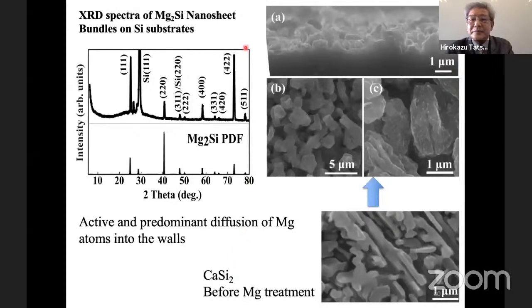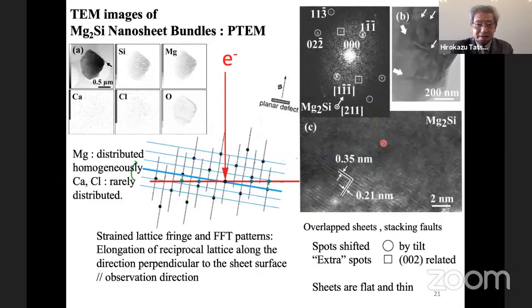So these are some images after the magnesium silicide nanosheets are formed. The shape is roughly strained or distorted, but the domain structure still remains. So the layered structure still remains. This is before the reaction, the CaSi2 domain structures. This is after treatment, the magnesium silicide nanosheet. It looks like one sheet is very thick, but these sheets are easily exfoliated from each other to become thinner layers. So this is a TEM image